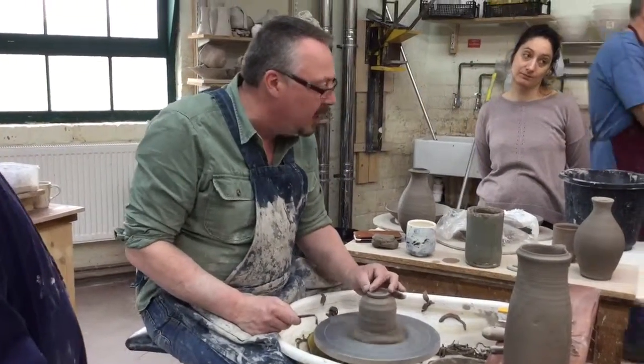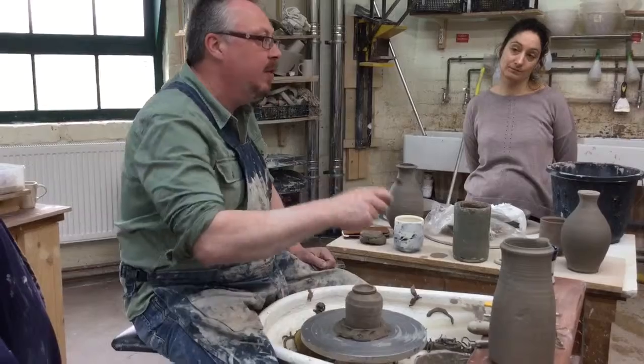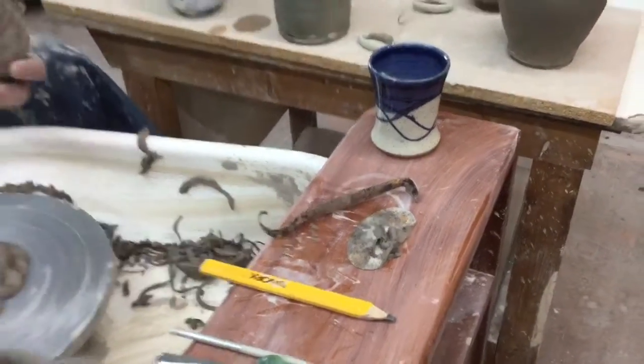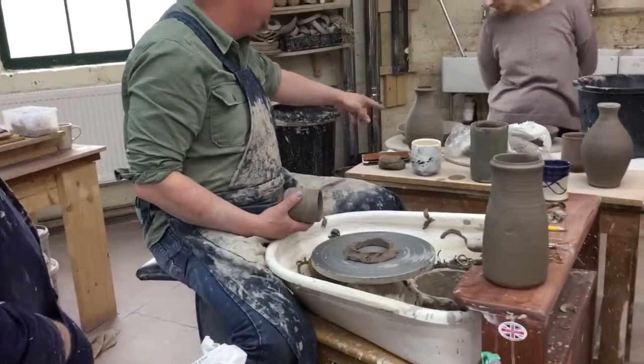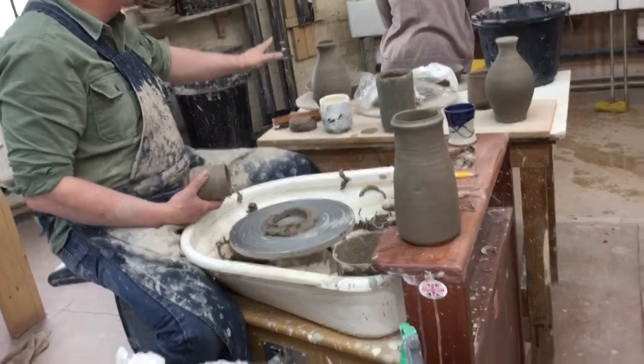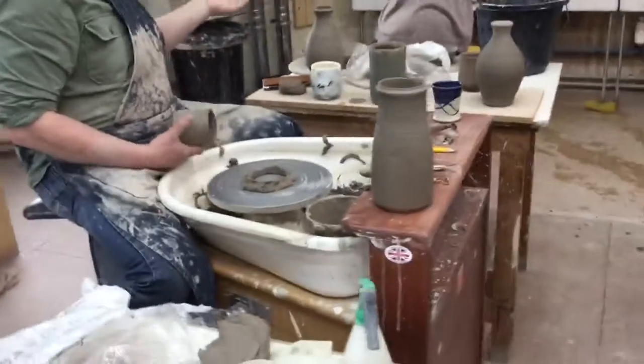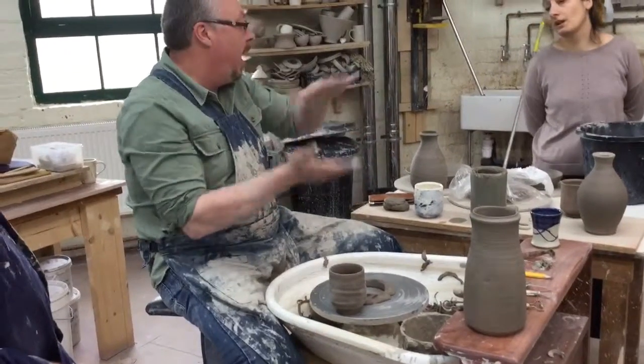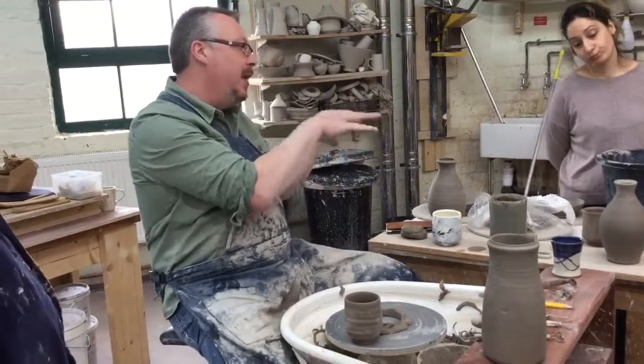When it's shuddering, is that generally because you're turning it a bit too dry? I find it's because the consistency of the base you're turning is for some reason uneven. You'll find it's beneficial, certainly when you're turning one of those pots, that you're in danger of the rim drying before the middle of the base. So as soon as the base is solid, you wire it, flip it, and wrap it up in your bag. Just leave it for a day or two. It equalises, and then you can proceed to turn.